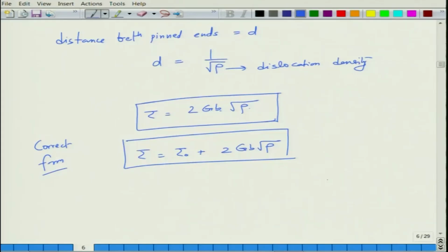So, you can see that these are the dislocations which are getting created. You can see that loops are continuously being generated and they spread in the material, newer loops are getting generated because you can see these black things which are nothing but pinning sites. As the stress is being applied, you create more and more dislocations, and they lead to an increase in the dislocation density in the material. So, this is essentially the operation of a Frank-Read source.